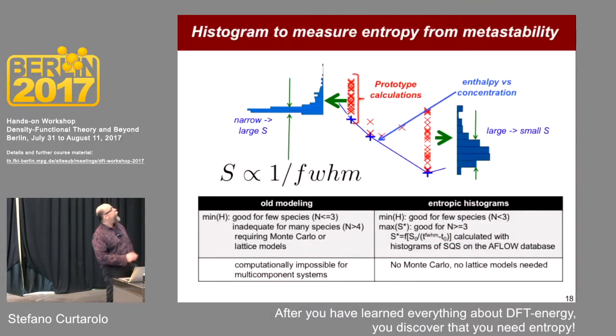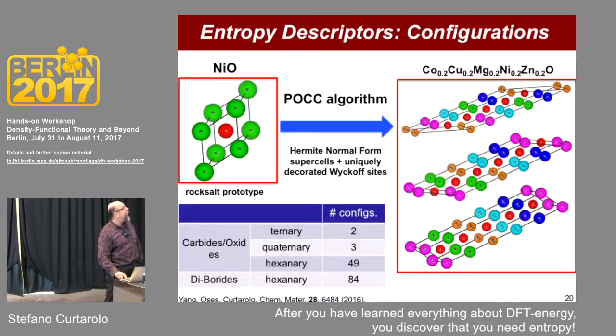Okay, listen one second. When I have the ground states here, I need to generate the spectrum of all the possible same-composition but messed-up structures. We wrote in the past a paper on how to get these things, and actually you should take note of this citation, because it tells you, if you have a lattice, how you mess up the lattice with partial occupation, to keep the same concentration and to generate all the thermodynamically excited states. Okay, there is a lot of technicality, and it's based on the supercell, particular supercells, which are the Hermite type of supercells.